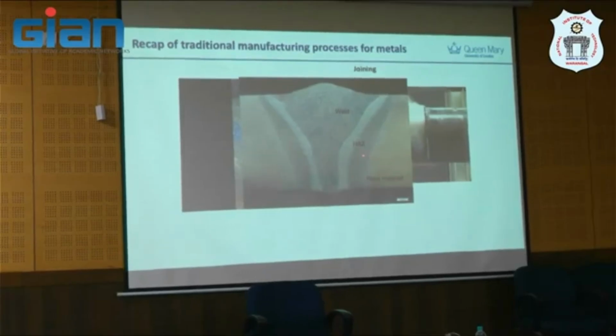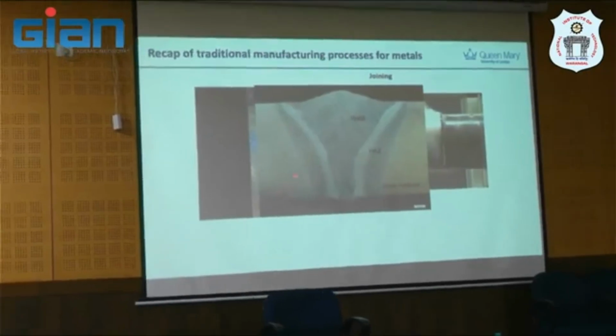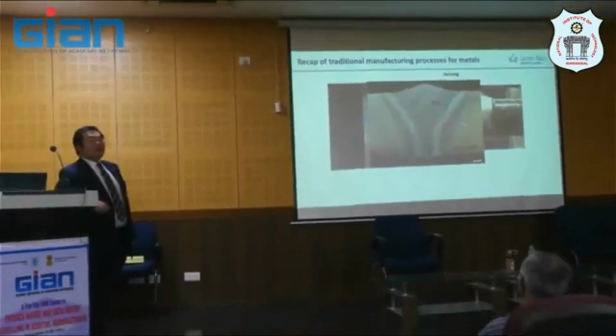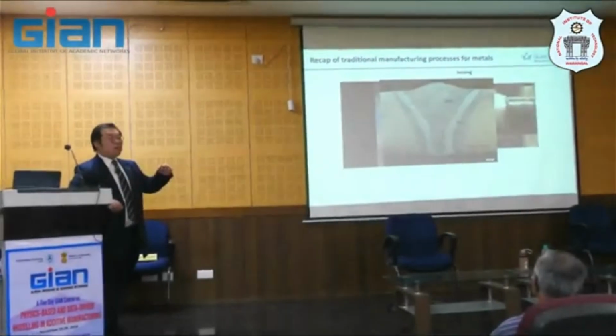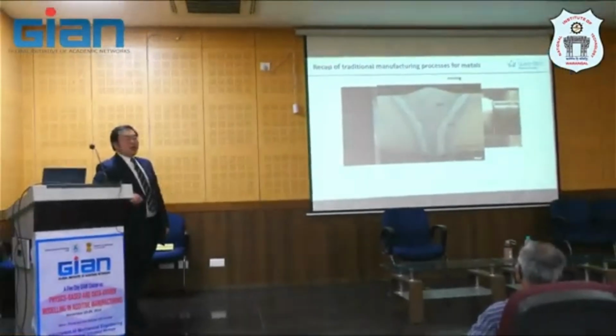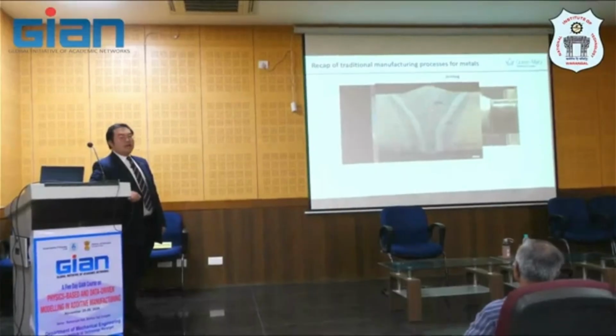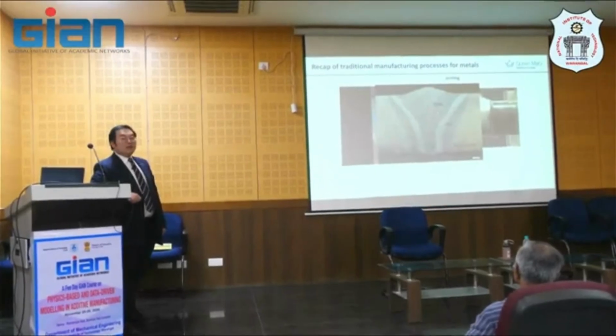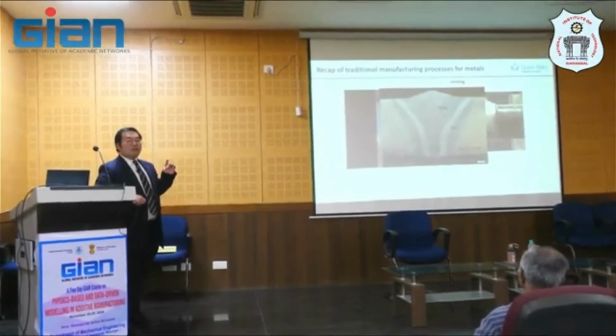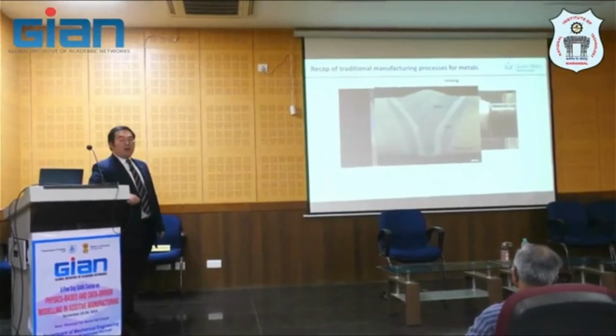The weld is the weakest area, because the microstructure in the joining part is different from the parent material and the heat affected zone. So here, phase transformation kicks in. The base material, heat affected zone and welded zone have different microstructures, which lead to different properties. And then you may get the weakest zone in this area. And this may be an issue if you don't manufacture with care.